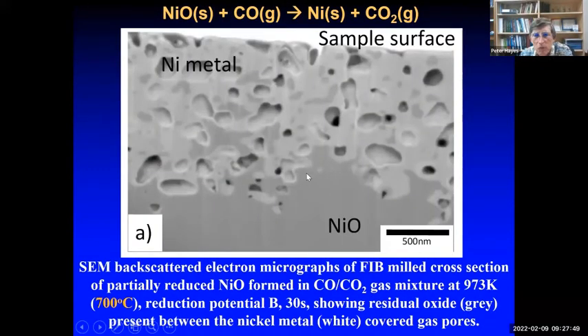If I go up to 700 degrees centigrade, we can see the shapes of the pores have changed slightly, and in this case we've actually cut the sample with a focused ion beam (FIB). So we've got a smooth surface here, not a rough surface. We've taken a smooth cross section, and you can see this is the sample surface, and you can see these pores tunneling their way into the nickel oxide. And in some cases, the tunnels have actually bypassed some of the nickel oxide.